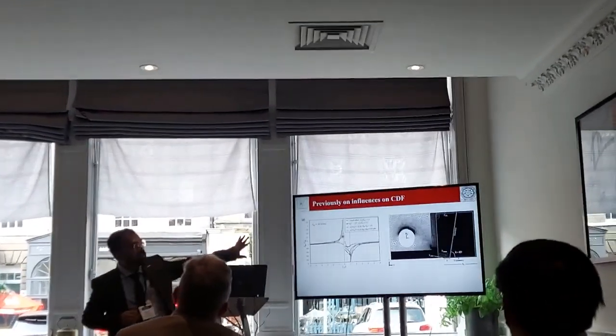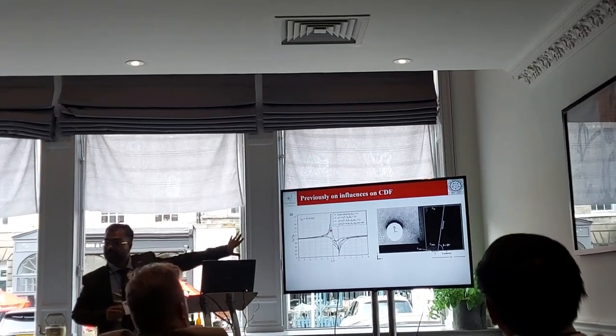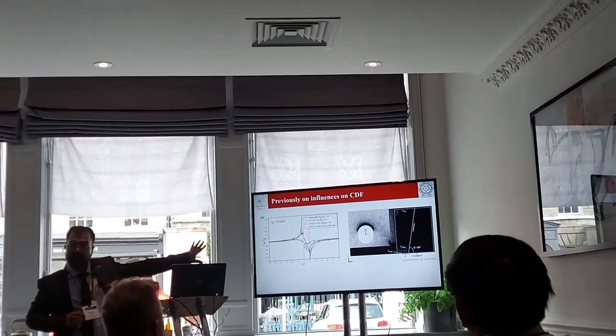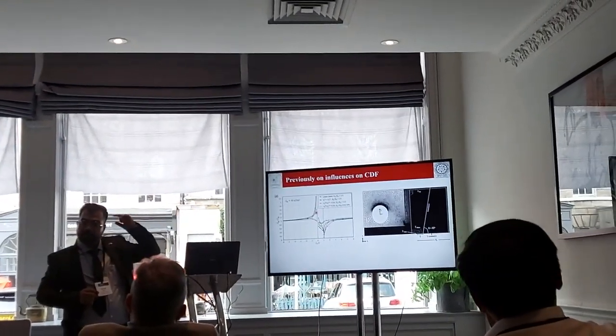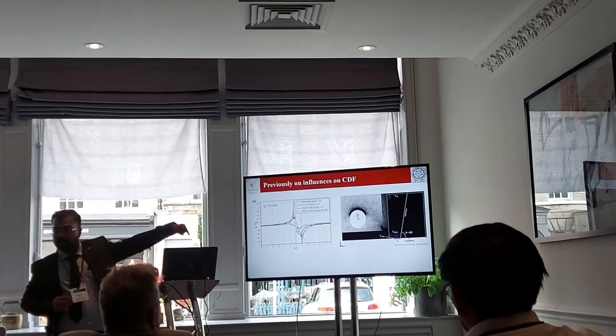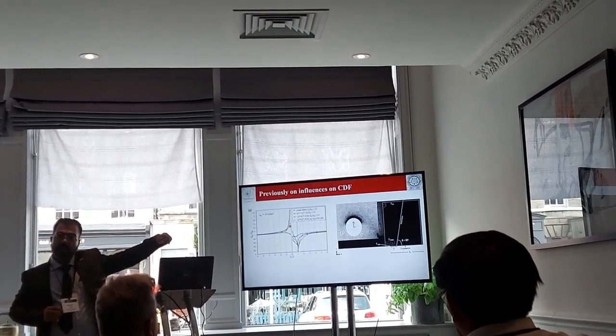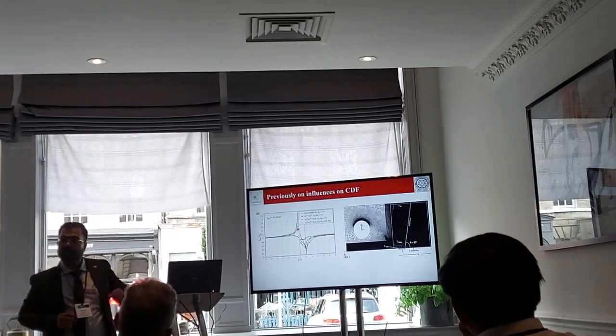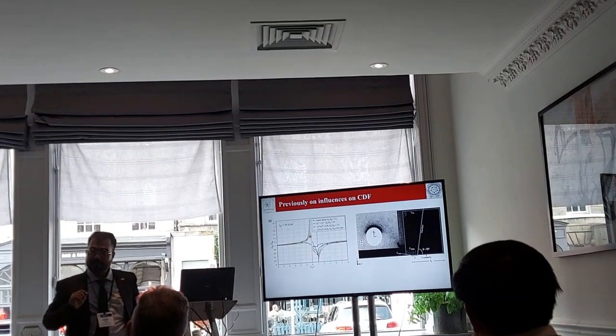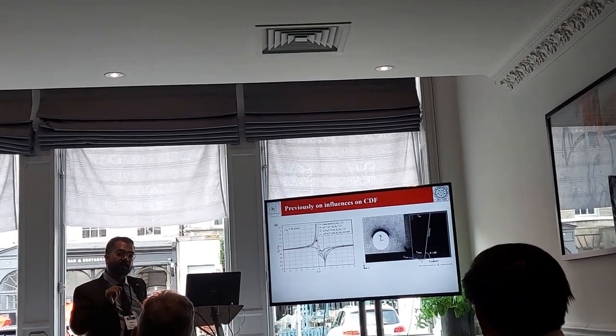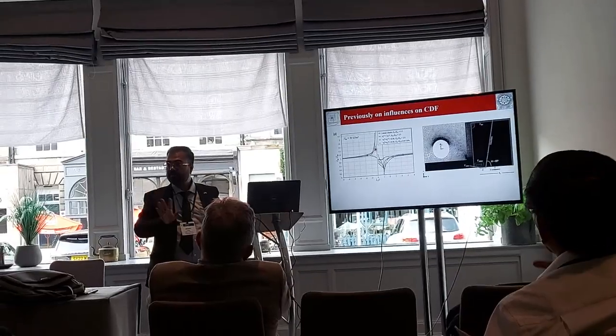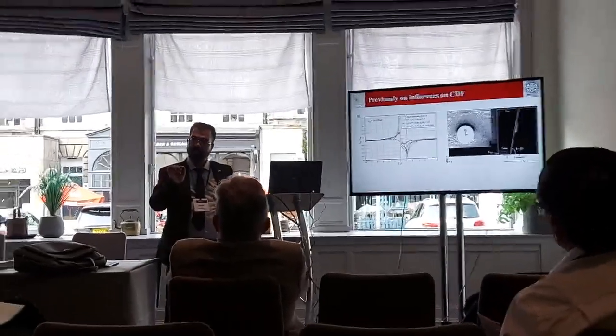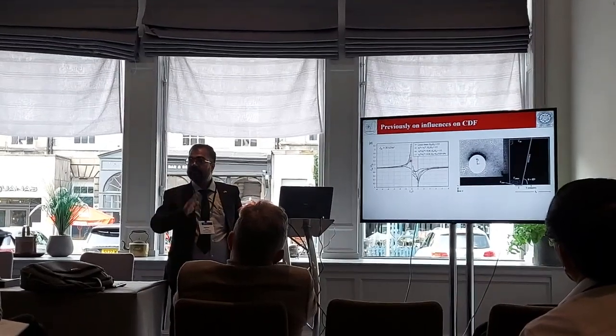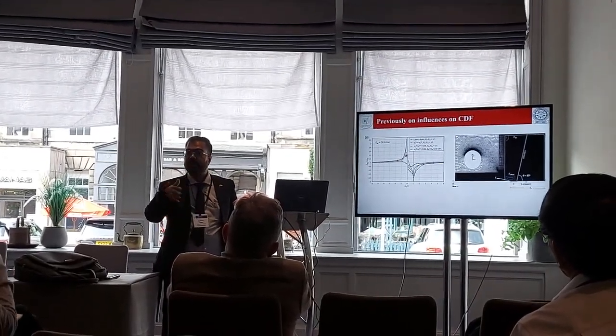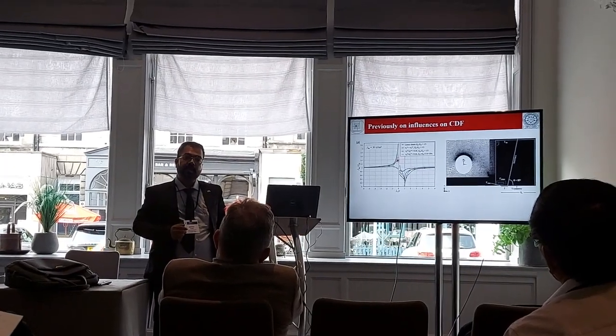For example, if I have steel in the matrix and the interlayer is aluminum, then this will be the case. But if I have aluminum in the matrix, which has lower Young's modulus or yield strength, then the plots will be different. The interesting point is where the crack driving force drops down. If it drops lower than the resistance offered by the material, then you can stop the crack. So you can use this phenomenon to arrest the crack without doing heat treatment or anything else. Just place a material, and you have to optimize the thickness, the distance, and the properties of the material you will use as an interlayer, and you can stop the crack.